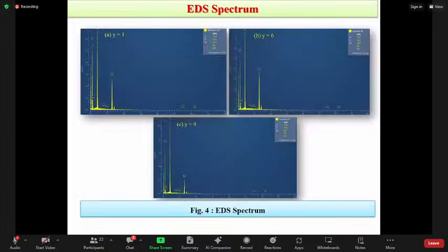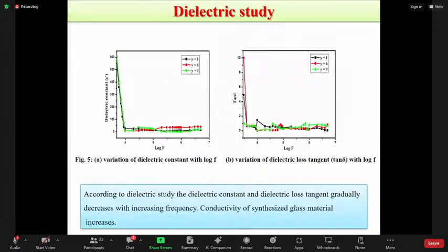Then we see the elemental detection analysis. In the elemental detection analysis, boron, iron, oxygen, phosphorus, and tellurium are present. There is no other peak present in the EDS. Hence, it shows the purity of the sample. Next, we see the dielectric constant.